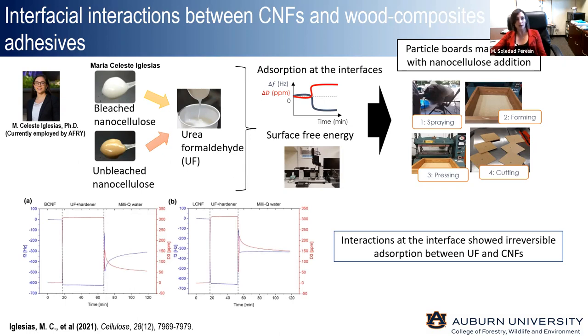So what we saw with our quartz crystal microbalance, for those of you who are not familiar, is basically a quartz piezoelectric sensor that will resonate at a certain frequency, and it will have our nanocellulose. On the left, you will see the bleached nanocellulose versus LCNF, meaning the lignin containing nanocellulose or unbleached nanocellulose. Then we expose this to a resin of urea formaldehyde with hardener, and a dampening in the frequency of this surface will relate to an increase in mass, meaning interactions of the cellulose with the resin. And by rinsing that, we will have a total adsorbed or irreversible mass adsorbed on the surface. What we saw in this case was that the lignin containing nanocellulose was interacting slightly more with the urea formaldehyde resin, but also more stable over time.